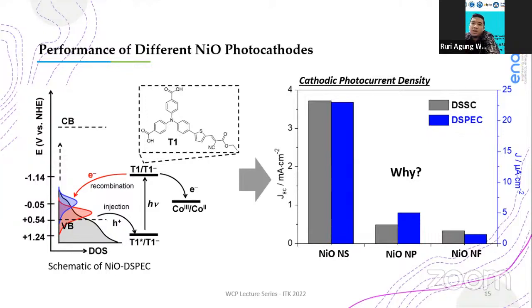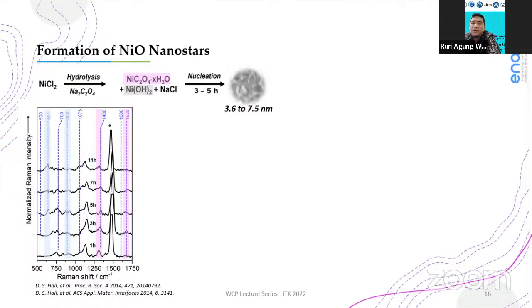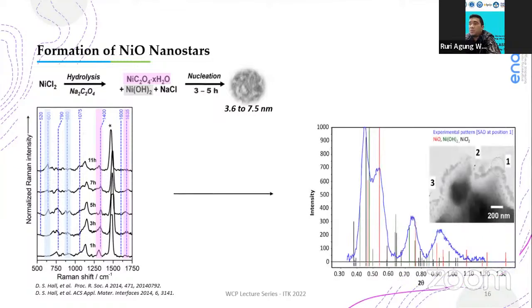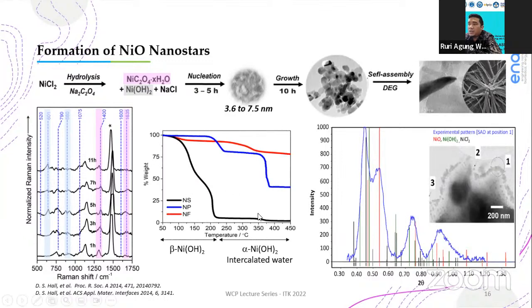To unravel the origin of this discrepancy, we have characterized the specific surface area, the porosity, microstructural, and also electronic properties. For example, here we first monitor the formation of nanostars during the synthesis using Raman spectroscopy and TEM EDX. And from the Raman spectra and also EDX, both indicate the formation of beta nickel hydroxide forming the nickel oxide nanostars. And this is corroborated by thermogravimetric analysis, in which nanostars, here the black one, underwent significant mass loss at a lower temperature due to the evaporation of the surface water molecules, which is typical for the beta phase. While the other structures, for example, nickel oxide nanoparticles and also nanoflakes, decompose at higher temperatures, which means the water molecules are trapped within the interslab spacing of the alpha polymorph.